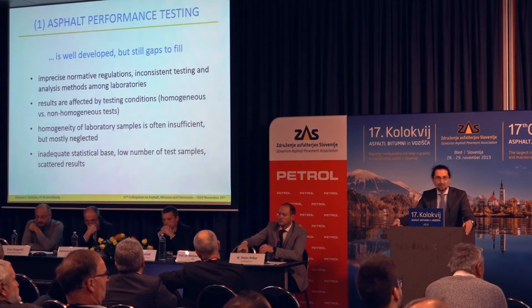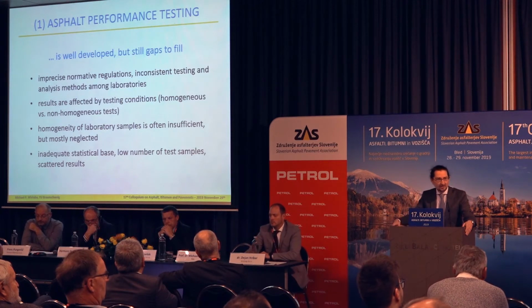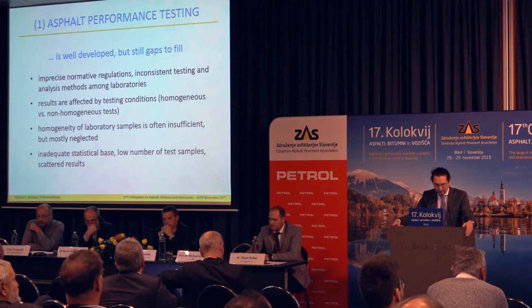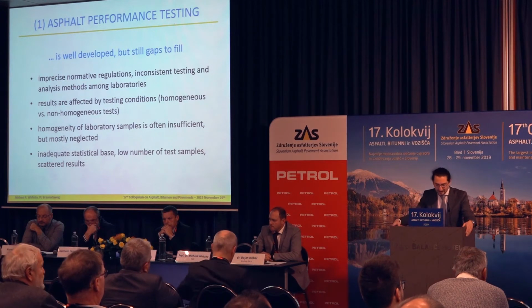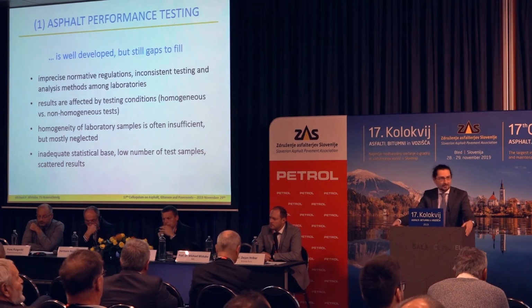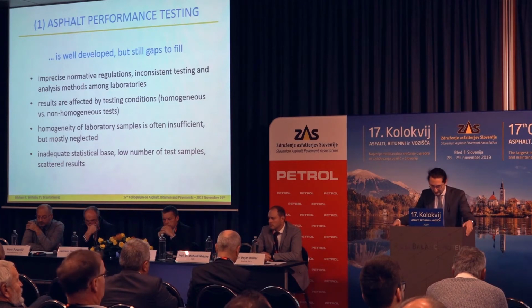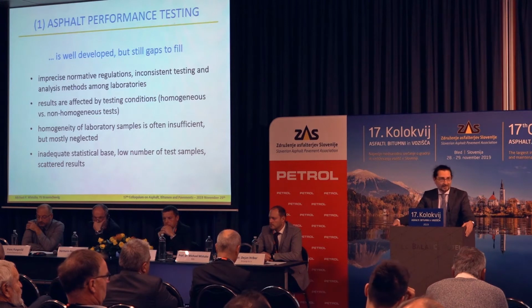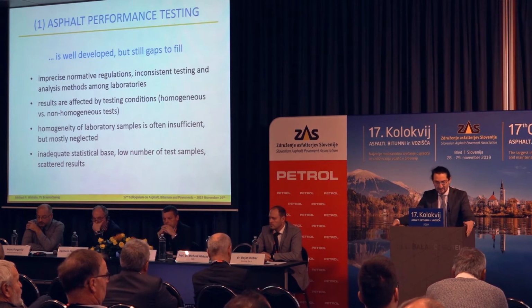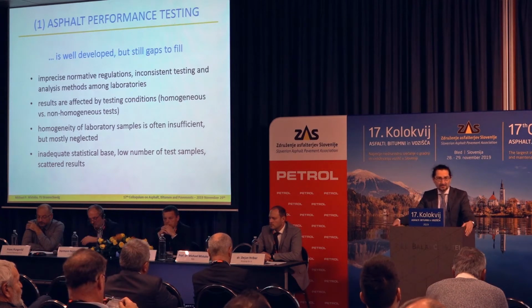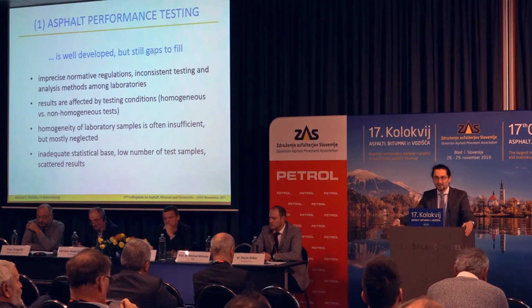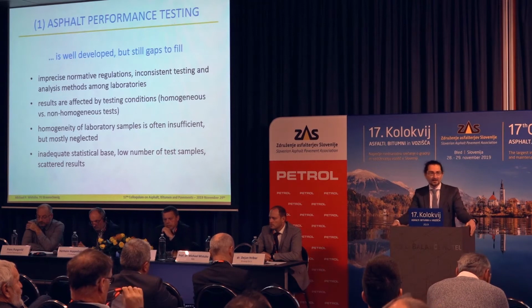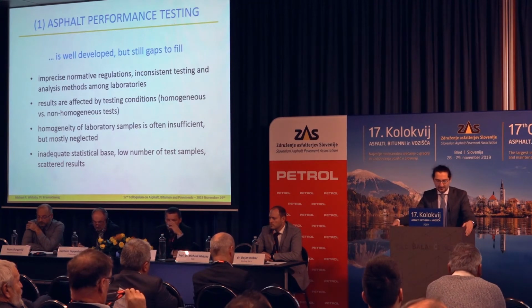And this set of experiments is rather well developed, because the development started already maybe 50 years ago, and significant contributions also came from former colleagues of my institute, and they tried hard to put together a set of testing equipment which is nice and which can predict performance of the road already by testing the materials in the laboratory. Even though this is a nice tool, there are still some knowledge gaps to fill because, for instance, normative regulations are not precise enough to guarantee that all laboratories get the same results. For example, when it comes to fatigue testing, there can be differences among laboratories by more than 100%.